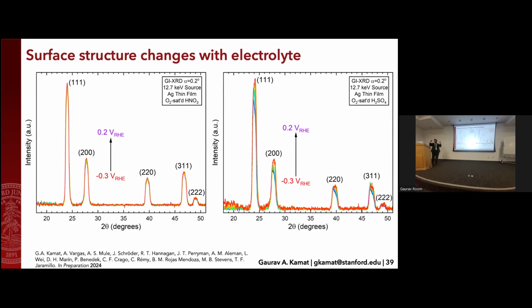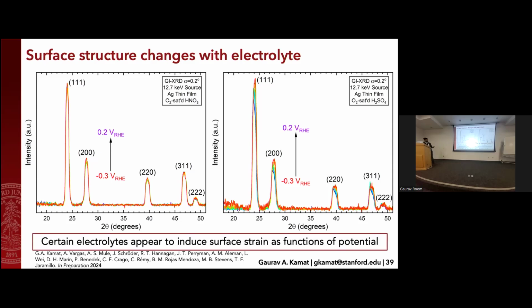So as the silver atoms nearest your surface either start to stretch or contract depending on what's going on at the surface, it seems like your anion actually has some effect and some role in causing changes to your silver surface. So certain electrolytes appear to induce surface strain as a function of these applied potentials. Now, that was everything we did. I didn't mention the other study on the orientation of the different crystallites, but those were the main takeaways that we found in terms of just the crystallinity.